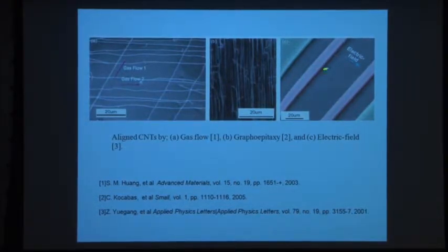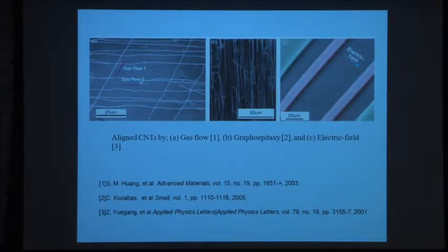You can apply a field between two contacts, and then the nanotubes will grow in that direction. Exactly the same as the way when you get a field growing in the sheath field. So you've got a way now of actually controlling the direction the nanotubes grow, even though we still can't control the chirality and the actual diameter exactly every time we grow them.